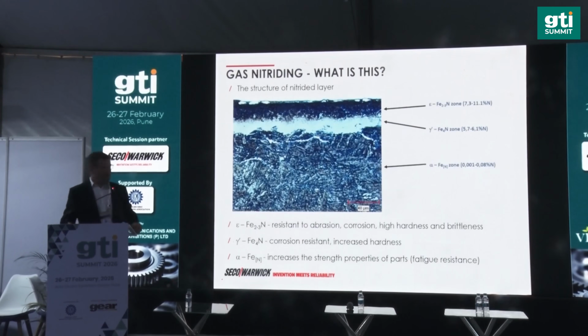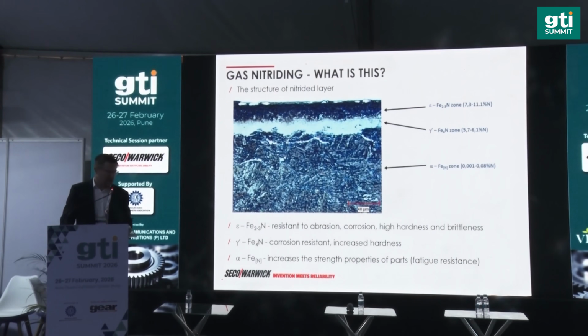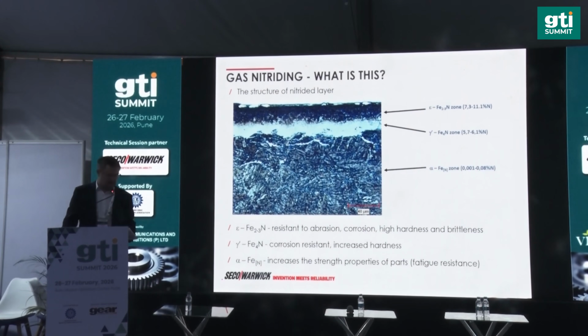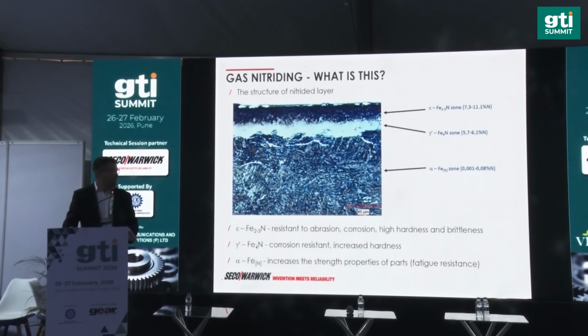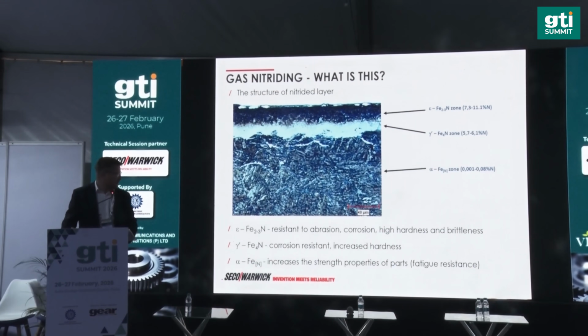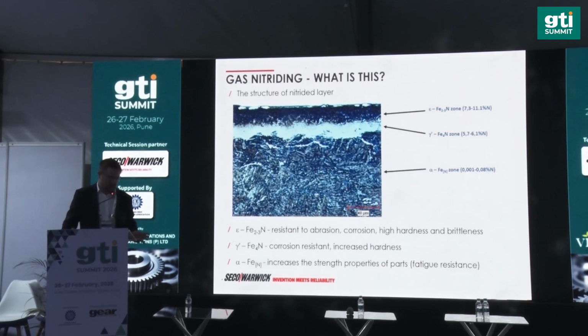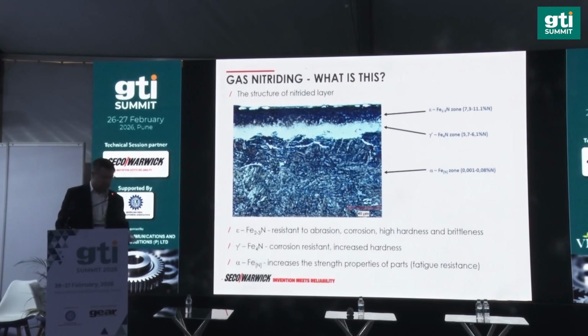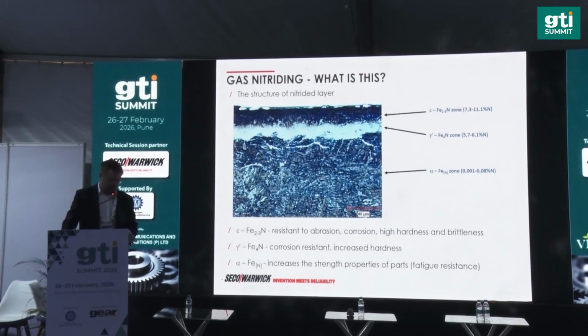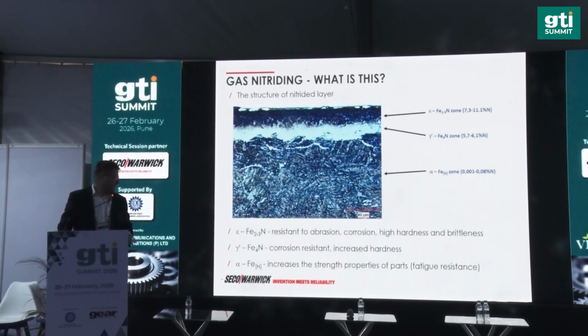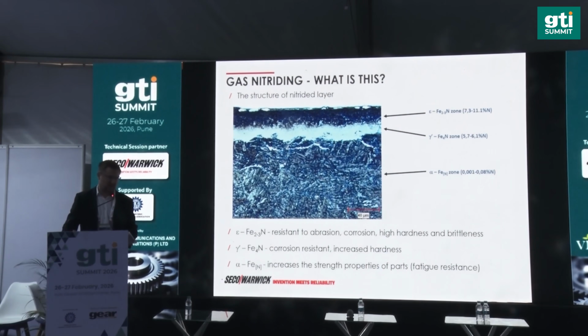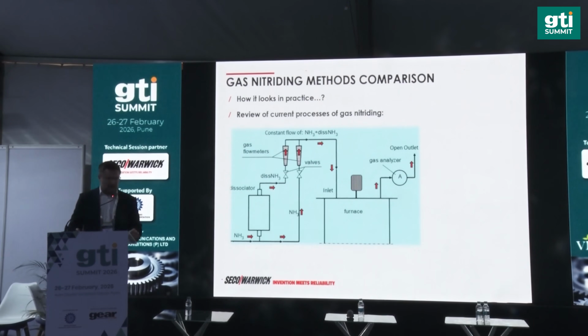So as a result of the process, we are achieving the nitriding layer, which can be composed of three phases: epsilon, gamma prime, and alpha. You can see the features that each particular phase is responsible for, and based on the requirements, we can compose the layer accordingly, having in mind features like corrosion resistance, or of course, in the case of gears, usually to increase the fatigue resistance. So how does it look in practice?